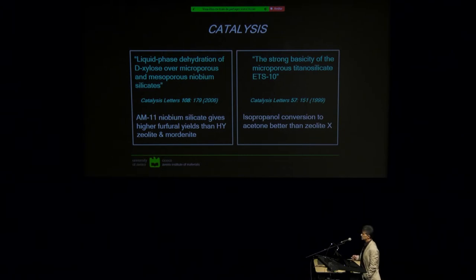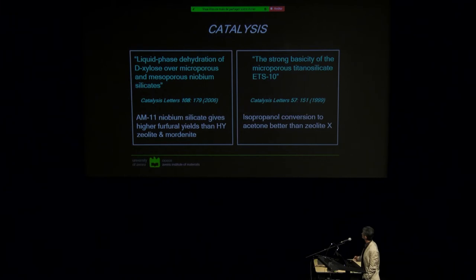And of course, catalysis is another field of applications. We did a lot of work on heterogeneous catalysis. And for example, using a certain niobium silicate, we called AM-11, we have higher furfural yields than obtained with zeolite HY, or mordenite, or perhaps using the titanium silicate ETS-10, we were able to convert isopropanol to acetone with better yields than zeolite X. So in a number of cases, our materials actually perform as heterogeneous catalysts better than more